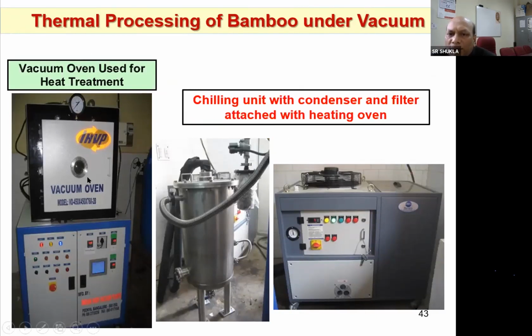This is the kind of chamber which we are using in the lab for thermal modification of bamboo under vacuum. Vacuum is required because we don't need to have oxygen when we are raising the temperature of the bamboo to 150 to 240 degrees centigrade. Otherwise, bamboo will start charring and it will degrade the quality of the bamboo. So oxygen should be removed, and a partial vacuum is to be created inside this chamber. This is the kind of condenser and chiller. Whatever gases are coming out from the bamboo need to be condensed using this chiller.